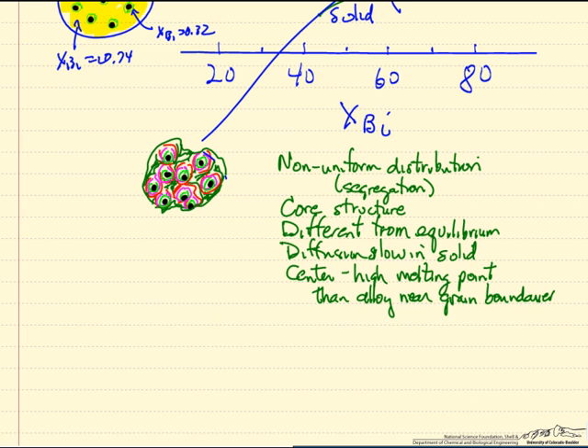The center, the black dots represented here, have higher melting points than the grain boundaries, the region between these particles. The final thing is the details of what this line looks like. This non-equilibrium line is going to be a function of how fast we cool the liquid. If we cool really slow, we're closer to the equilibrium line. If we cool fast, we're further from the equilibrium line. The important point here is that this affects the structure of the solid when it's not uniform, but has a gradient of concentrations.